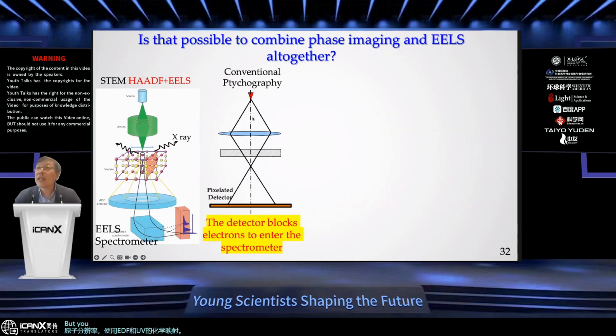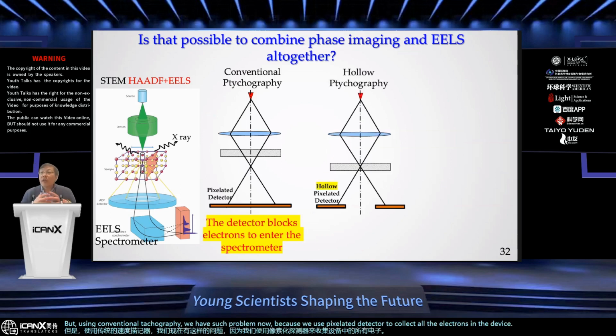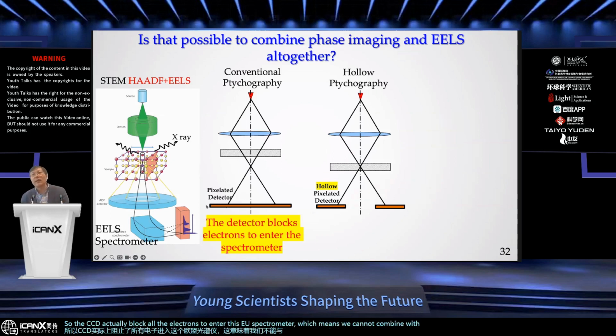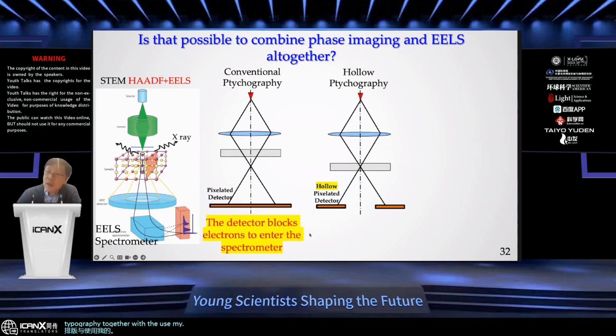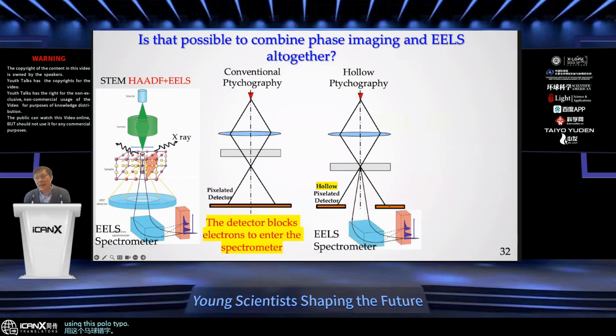But using conventional ptychography, we have a problem, because we use a pixelated detector to collect all the electrons in the diffraction pattern. So the detector actually blocks all the electrons from entering the EELS spectrometer, which means we cannot combine ptychography together with EELS mapping. Now we have come up with a new method. Can we combine ptychography together with EELS using a hollow type of detector? So that we can combine this ptychography imaging together with EELS mapping.